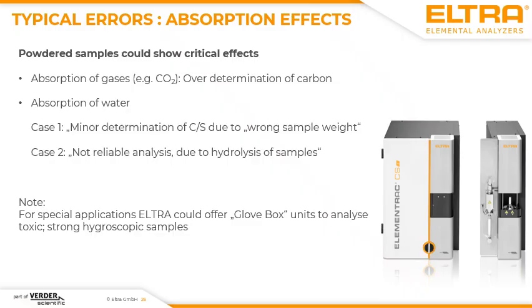When you have the job to measure samples which have a strong hygroscopic effect, then you can't perform this kind of analysis in a conventional carbon sulfur analyzer. Then you have to use a glove box unit with separate combustion unit and detection unit. Then you can place a combustion unit in a glove box, which can be prepared with an oxygen-free atmosphere, and also an atmosphere which is free of water.